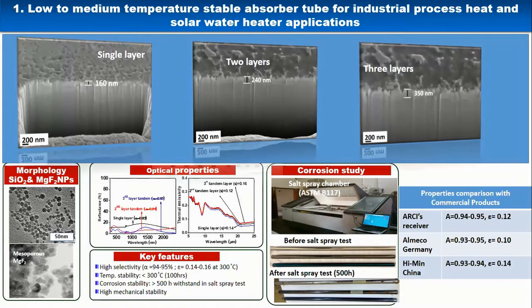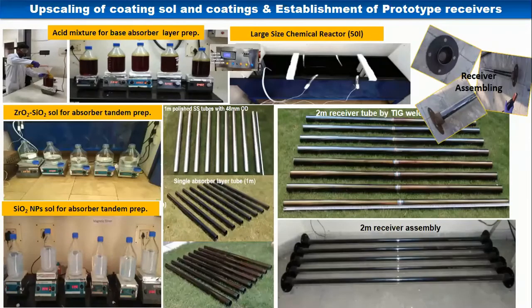Most PVD type coatings put on 6 layers of different metal oxide and metal coatings to get more optical absorptance. Whereas in our case, all 3 layers have a total thickness of around 350 nanometers. With this compact thickness, we get a low thermal loss property. I will show that thermal loss property when we complete our validation process. So this is the upscaling.